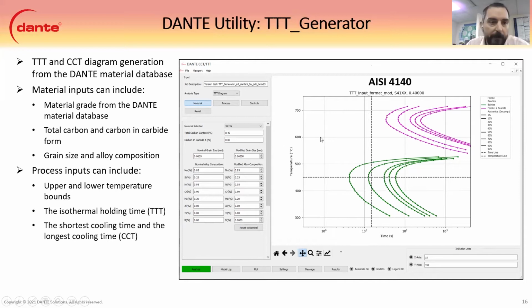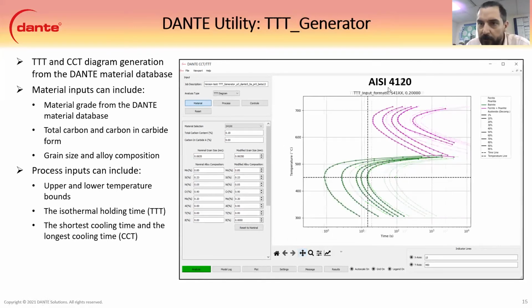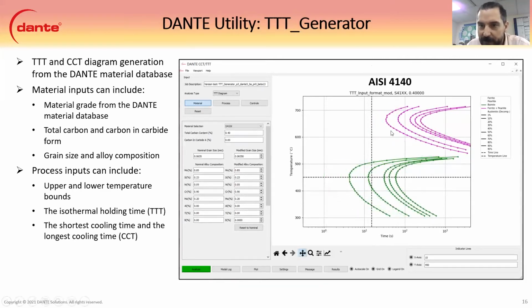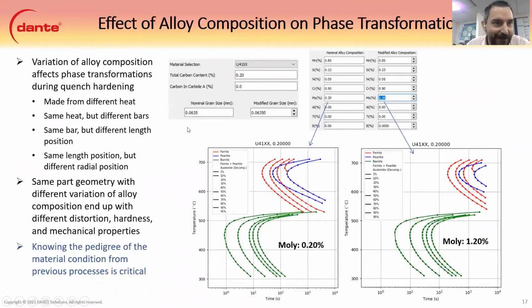And then if we were to modify this chemistry here from 4120 to 4140, you can see you expect that the phase diagram would move to the right. And as you can see, using the same marks, we move completely out of the ferrite and pearlite, which is at this top level here, and we move more into the bainite areas here. The green is the bainite, and the purple is the ferrite and pearlite. Hopefully that makes sense for you.